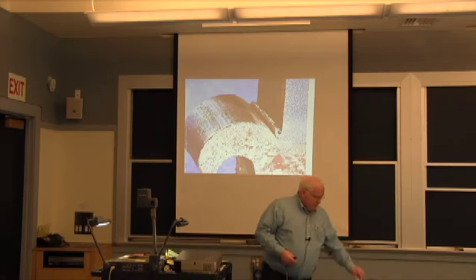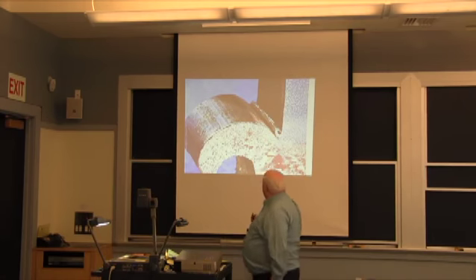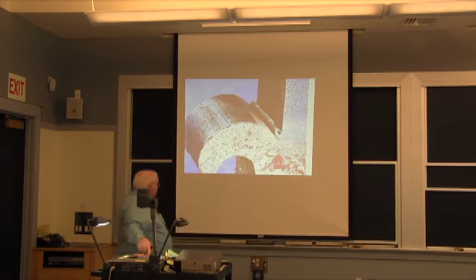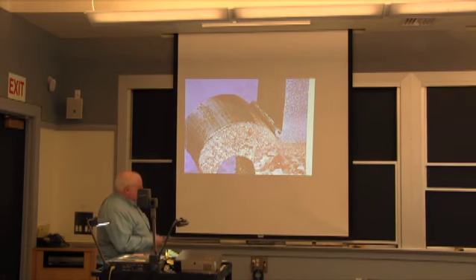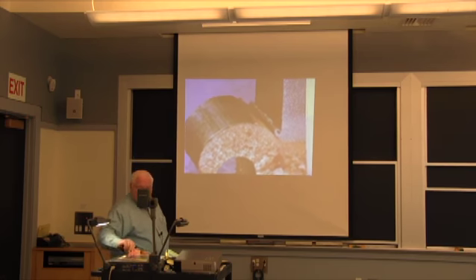Now, another thing, we talked about friction welding, and someday they're going to make one of these things that automatically gets the right lighting. This actually is a linear friction weld between steel and copper. Steel and copper don't like to mix very well in the solid state. So you can make a dissimilar metal joint, and you can see the difference in mechanical properties here, and up here you can see you transferred a little bit of steel and you kind of broke the bond as you're going along.